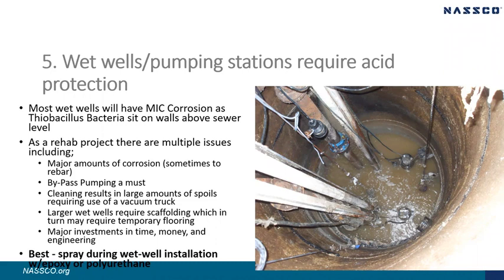Bypass pumping is a must. Pressure cleaning of the corrosion can result in significant amounts of granular spoils that must be removed from the bottom of the structure. We have actually used vacuum trucks in the past to suck up all the spoils. Larger wet wells require the construction of scaffolding, and sometimes temporary flooring is required, which further increases cost and delays.